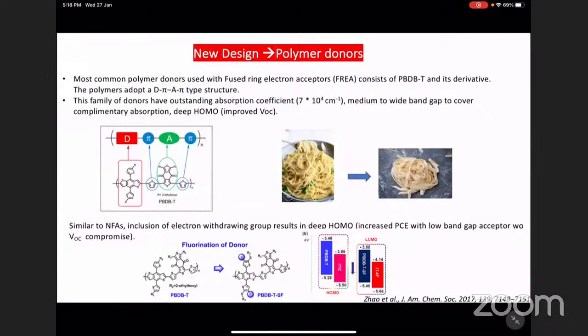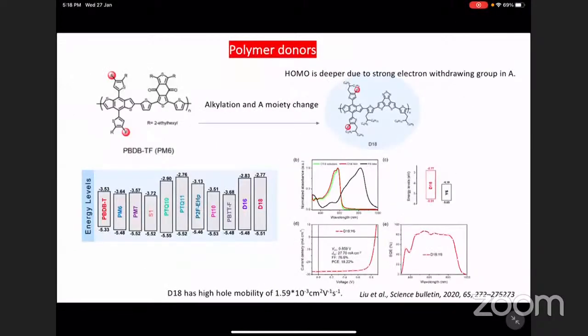So these things were going hand in hand, and this is the molecule which has got various different forms, and the efficiency is here for the D18 molecule. You look at the mobility number. It is 10 to the power minus 3 centimeter square per volt per second. I showed you earlier for the P3HT and PPVs, those are minus 6 to minus 7. So there's a 2 to 3 orders of magnitude difference in the SCLC mobility of the donor system. It's not FET mobility, it's basically space charge mobility. So those numbers suggest that, and the fill factor is touching 80%, and complementary absorption is coming from the acceptors.